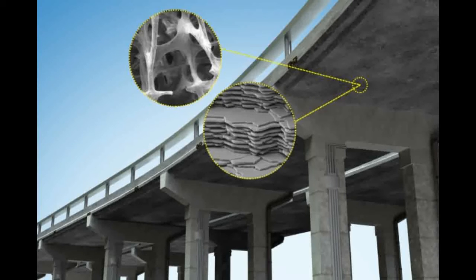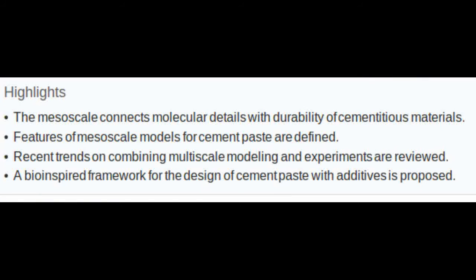To see whether volcanic ash would improve cement-based properties, engineers following the group's framework would first use existing experimental techniques such as nuclear magnetic resonance, scanning electron microscopy, and X-ray diffraction to characterize volcanic ash as solid and pore configuration over time. Researchers could then plug these measurements into models that simulate concrete's long-term evolution to identify mesoscale relationships between the properties of volcanic ash and the material's contribution to the strength and durability of an ash-containing concrete bridge. These simulations can then be validated with conventional compression and nano-indentation experiments to test actual samples of volcanic ash-based concrete.